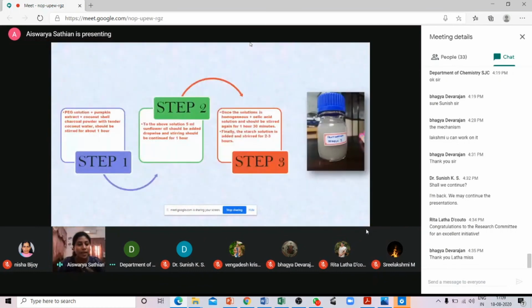In the synthesis part, I did the double emulsion solvent evaporation technique. I took all the materials which are not harmful and which we use in daily life. First of all, I took the pumpkin skin, polyethylene glycol, oleic acid, starch, and coconut shell charcoal powder, which is dissolved in tender coconut water. In the synthesis step, I took the PEG solution and mixed the pumpkin extract, and then I added the coconut shell charcoal powder, which is dissolved in the tender coconut water.